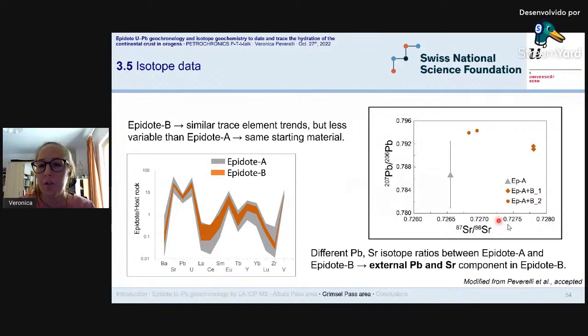But if we look at lead and strontium isotope data measured in epidote A grains and epidote microseparates that mix epidote A and epidote B in different and unknown proportions, you see that epidote A is isotopically different than epidote microseparates. We may infer that this indicates that epidote A is isotopically different than epidote B, and this is more readily explained by invoking the addition of external lead and strontium to the system during deformation. So how do we put everything together?